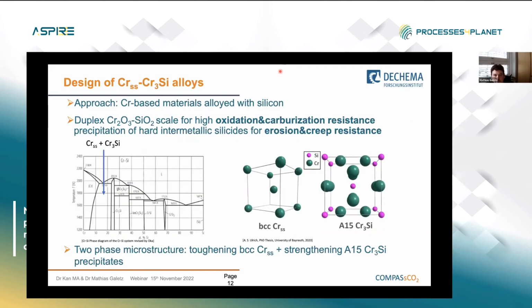You already got an introduction on the chromium-based alloys. Now we change the system a little bit and look at systems that are silicon alloyed instead of the aluminum and nickel alloyed systems. The big advantage usually is that for those systems, as you will see in a second, we form a duplex scale of chromia and silica that strongly improves the oxidation resistance and makes those systems interesting for not only oxidizing but also carburizing